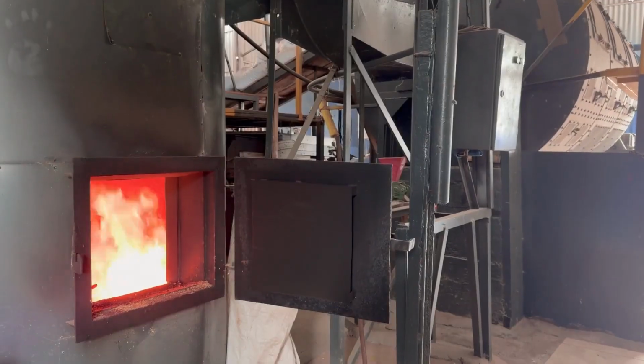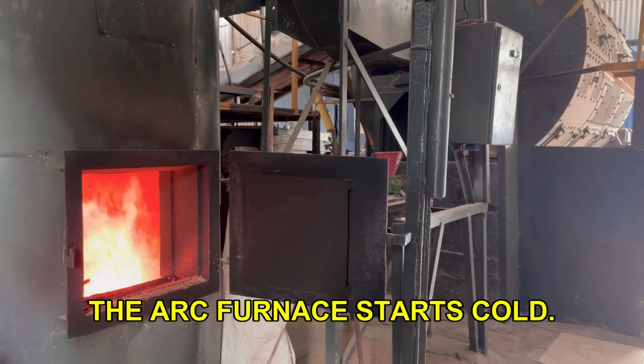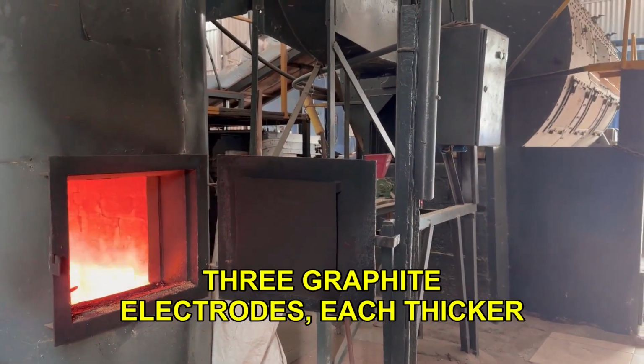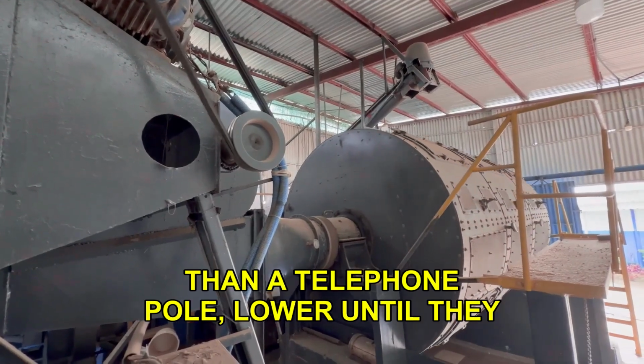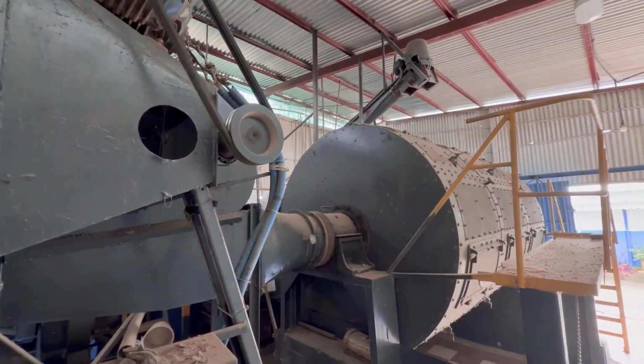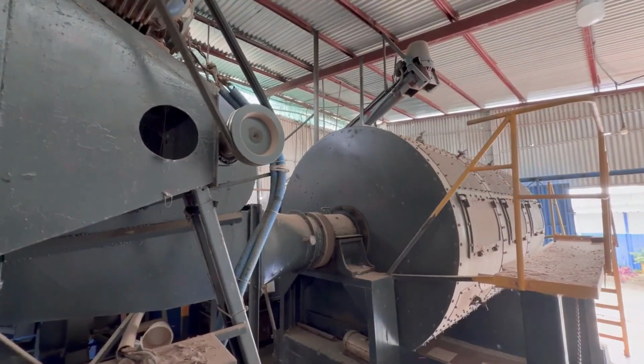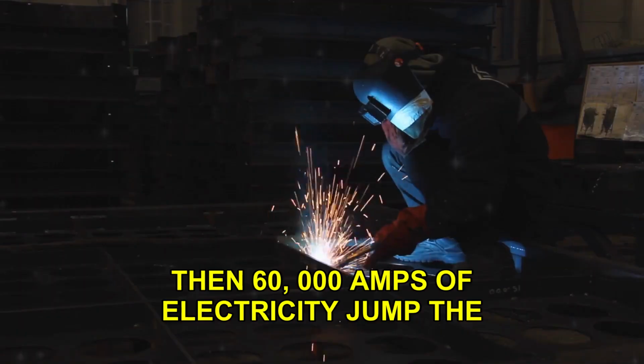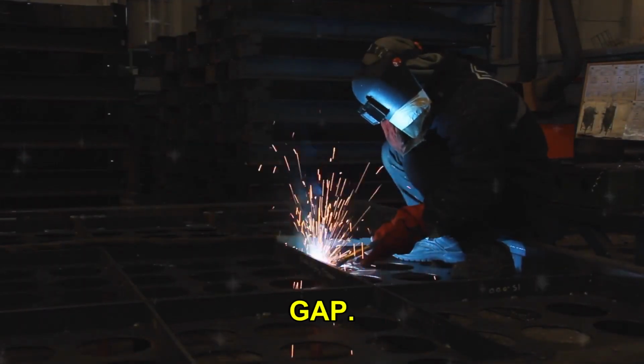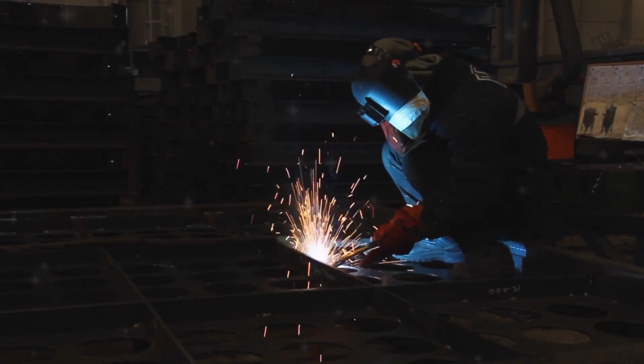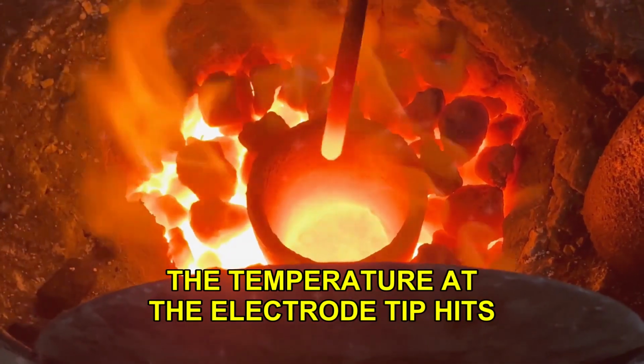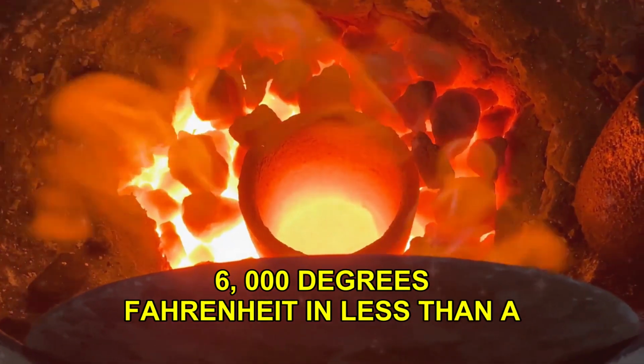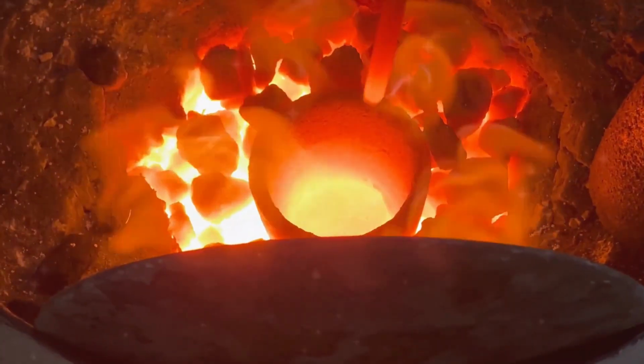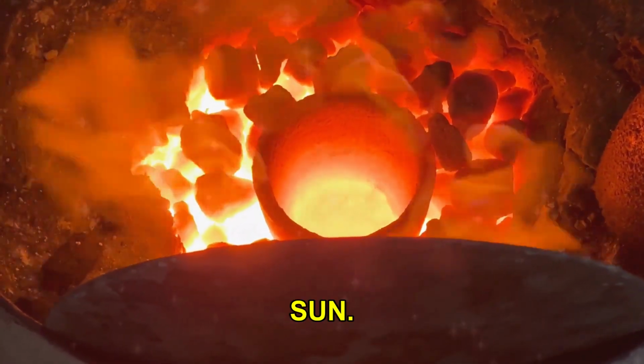Now look at the furnace. The arc furnace starts cold. 3 graphite electrodes, each thicker than a telephone pole, lower until they almost kiss the roof of the furnace. Then 60,000 amps of electricity jump the gap. An arc forms. The temperature at the electrode tip hits 6,000 degrees Fahrenheit in less than a second. That is hotter than the surface of the sun.